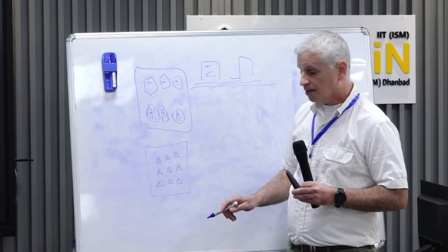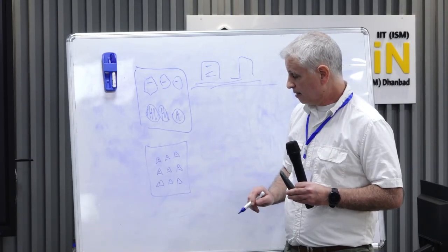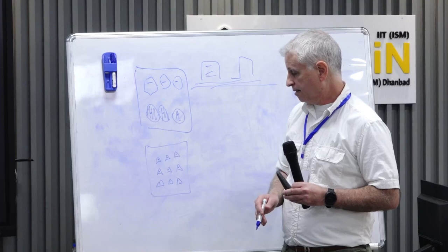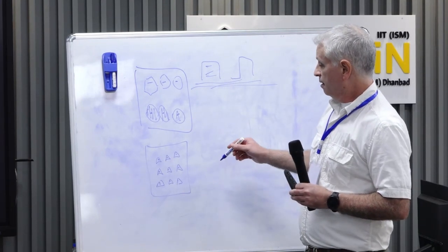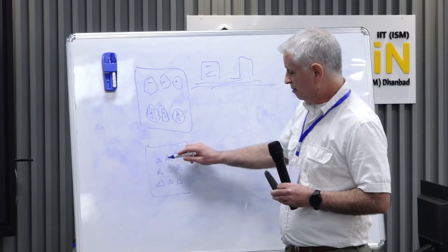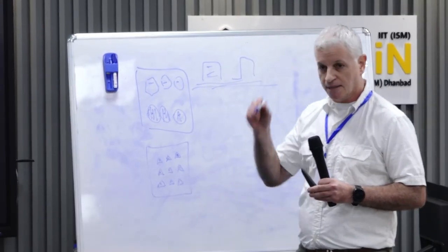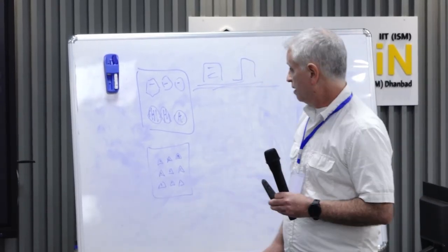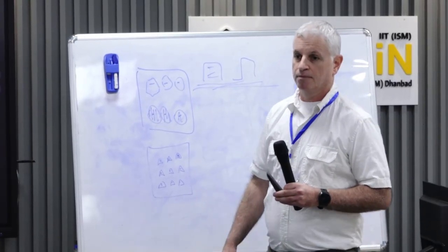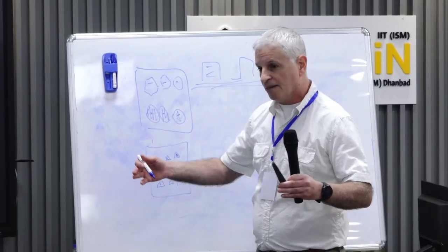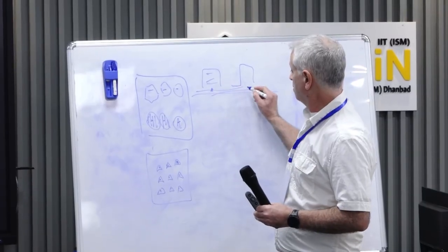In this case the pits are triangular because it's a TMD, and then they fill it. These methods are very similar in the sense that they nucleated the growth of the second material at defects. The only difference is that here they expanded the defect to a pit, and there they use just the defect in order to nucleate the growth.